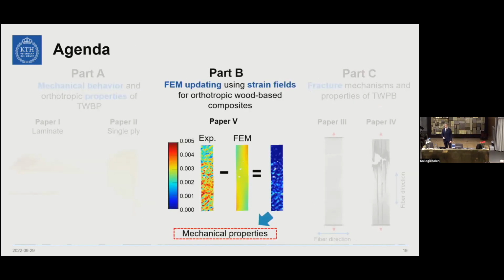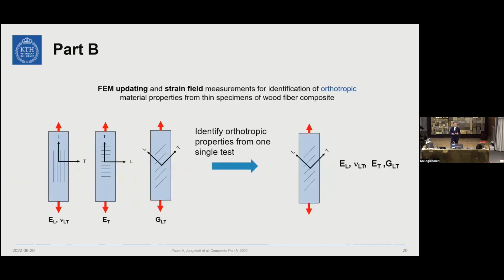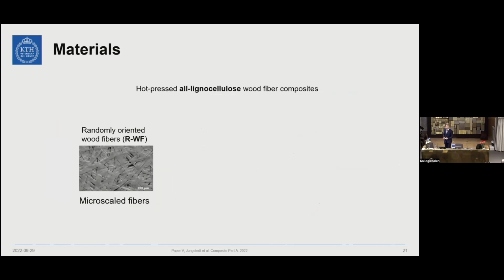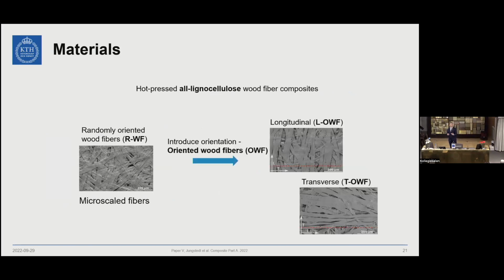So the second one, now we're gonna look at the method for, instead of doing 3 tests to characterize this material, we would like to use 1. So we could postulate material models to describe the linear behavior, but also if there is a non-linear behavior. So for this method, we will use wood fiber composites. So we take a wood fiber composite with a random orientation, and before making the material, we could introduce an orientation to the fibers, so it becomes orthotropic.